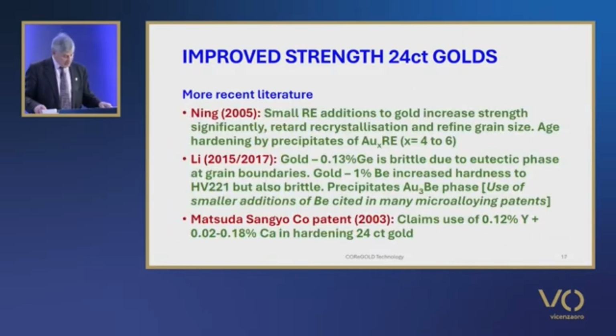We look at more recent literature on microalloy 24 karat golds. Further research has been published since my review in 2005. The effect on properties of rare earth additions such as cerium and gadolinium to pure gold and gold alloys has been reported by Ning. He showed that small additions to both pure gold and gold alloys increase the strength significantly and retard recovery and recrystallization, as well as refining the grain size.